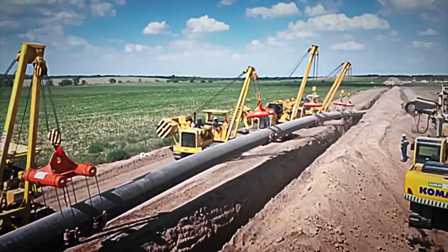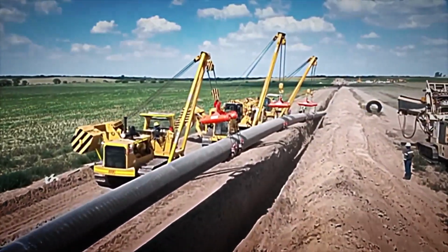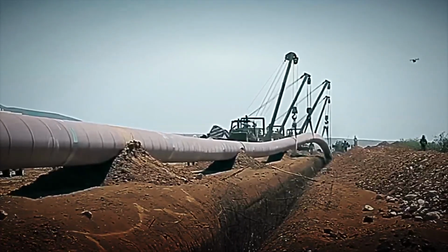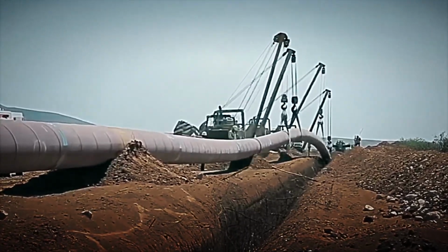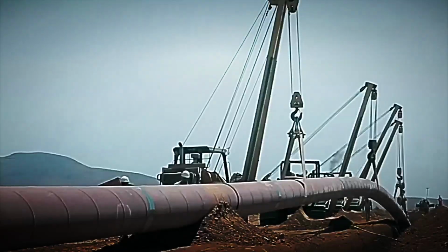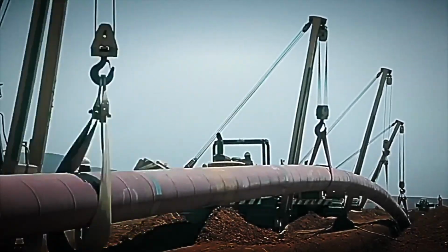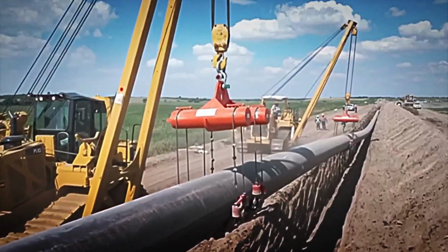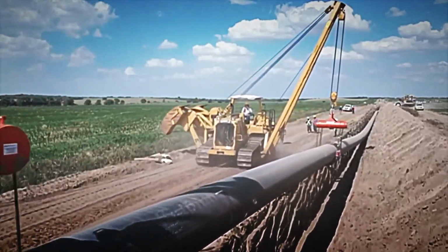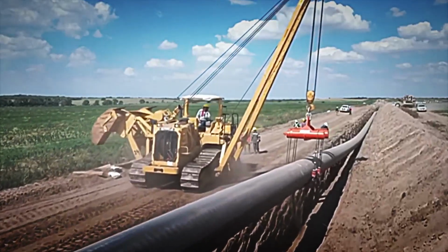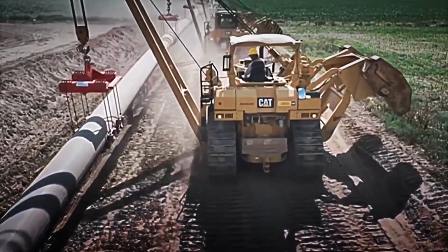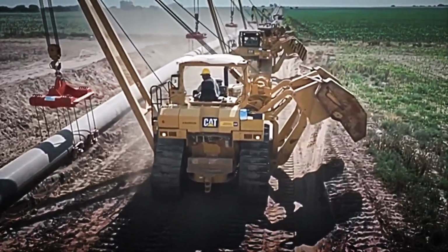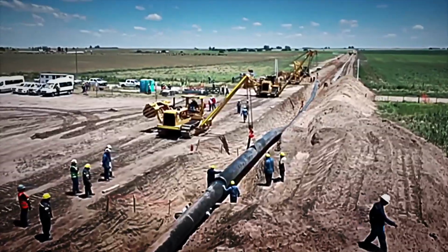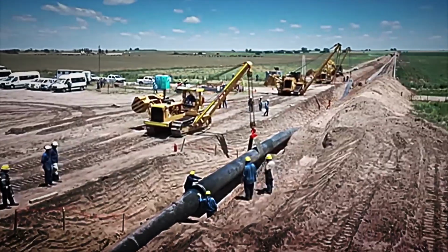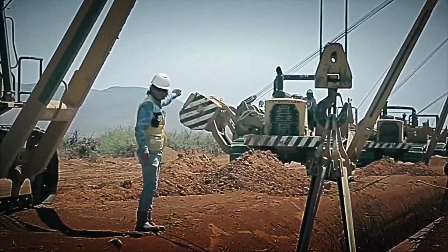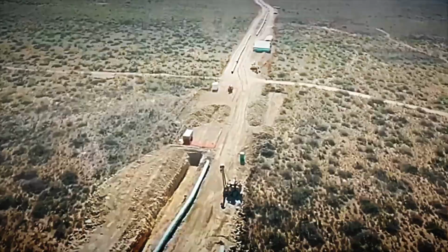When welding is completed, each joint is inspected with automated ultrasonic testing to confirm that no internal defects exist. Then, the joint coating team cleans the surface with abrasive sandblasting and applies a multi-component liquid epoxy coating, creating a durable, fully sealed protective layer before lowering the pipes into the trench and backfilling it. The assembled pipes are lowered into the trench using side cranes mounted on crawlers, vehicles specifically designed for constructing large diameter pipelines. Several side arms work in sequence along the line.